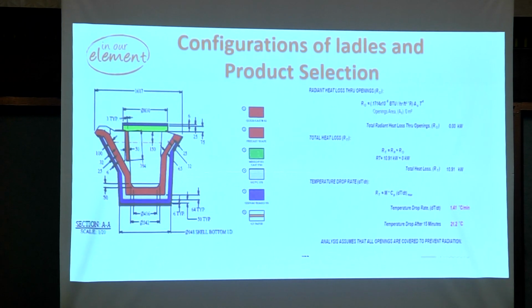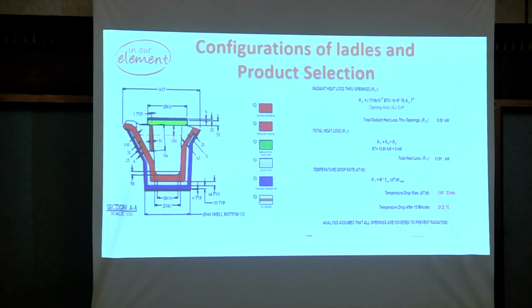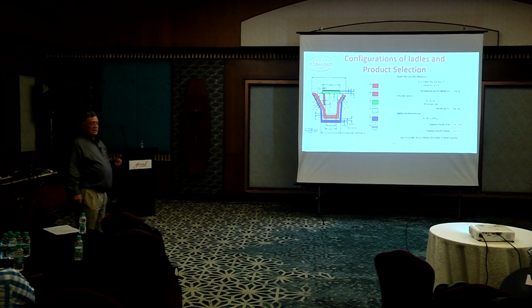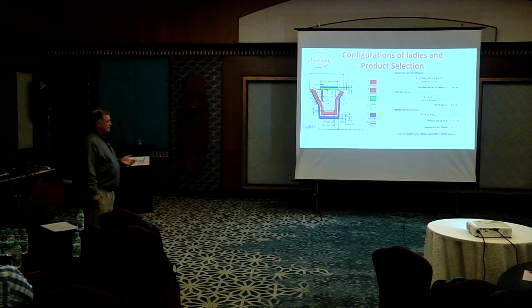And then if you have enough space, you can put board, you can put paper, and that way it really reduces your heat loss. But reducing heat loss is also good in a ladle if you have buildup problems, because the less heat you lose, the less buildup. Buildup is a function of heat loss, partly. It's a chemical issue, but it's also a function of that.